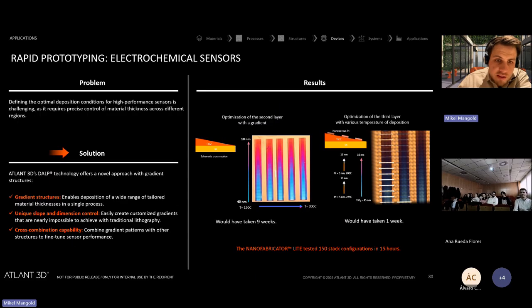Then here you can see that this was, I think, electrochemical sensors that you just coat on the titanium nitride substrate, titanium oxide, and on top you put some lines of platinum, and that is basically creating the sensor.